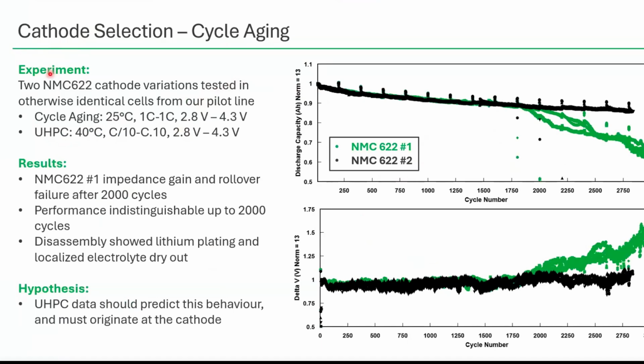In this experiment, we had two different cathode variations tested in otherwise identical cells, again from our pilot line. We did cycle aging at 25 degrees and UHPC at 40 degrees, again doing this UHPC cycling very slowly in order to just get the differences in electrochemical stability.